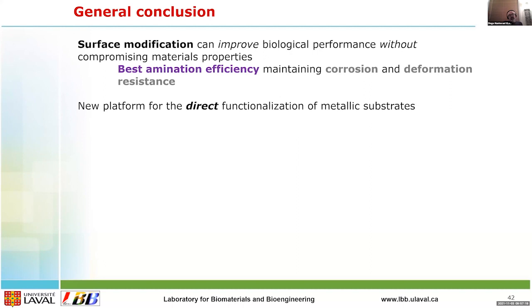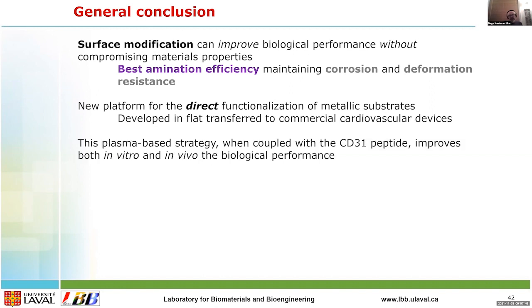So what I hope I was able to show you is that surface modification can improve the performances without compromising the properties. The best amination efficiency was able to maintain corrosion and deformation resistance. A new platform was developed for the direct functionalization of metallic devices. First we developed it on flat surfaces, and then we transposed it to real devices. It's a plasma-based strategy, plasma sterilized, so there is evidence it is much more interesting than wet chemistry, and when coupled with CD31 peptide coming from PECAM, it improves the in vitro and the in vivo performances.